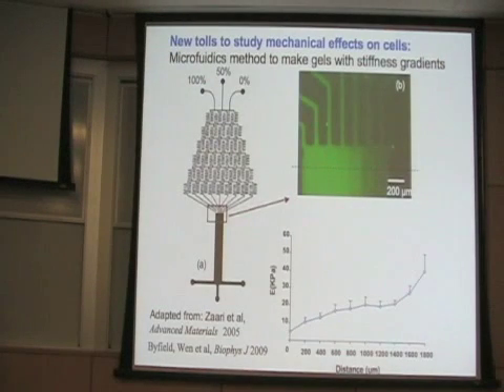In order to study this, we've recently started to try to improve the ability of doing these experiments, because it's a bit of a pain to make, as everyone who's done these knows, to make a bunch of these gels and to look at things separately. But it turns out you can use microfluidics to make gels with a gradient of stiffness by changing the concentration of the cross-linker for the linear polymer from which the gel is made. In this case, it's one of these polyacrylamide gels, but in principle, this can be any material that you can push through a microfluidics device.